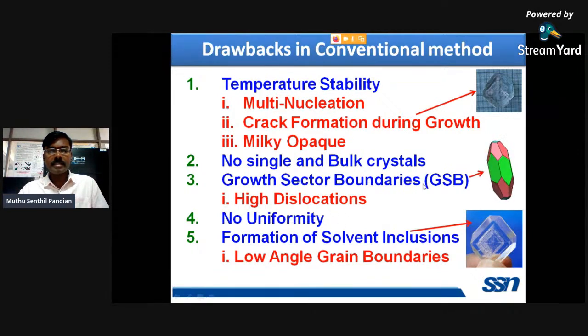And due to the growth sector boundaries, several dislocations appear in the conventional method grown crystals, and we cannot grow highly uniform crystals. The uniformity of the conventional method grown crystal is less. Why I am telling you, in my next few slides. And due to formation of solvent inclusions, low angle grain boundaries appear in the conventional method grown crystals. So these are some of the disadvantages of these conventional method grown crystals. Most of the solution growth people are choosing this conventional slow evaporation method. So multinucleation, crack formation, milky opaque regions, no bulk size single crystals, high dislocation, no uniformity, and low angle grain boundaries also appear in the conventional method grown crystals.